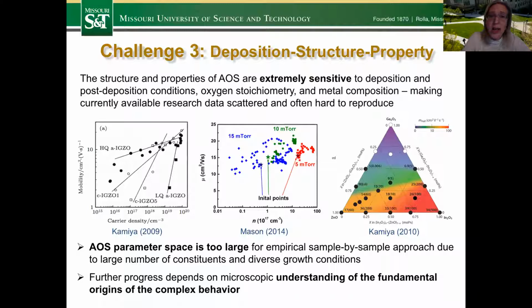Finally, challenge number 3. And these are complex deposition structure properties. So these materials have been studied for quite a while, and still there is a huge gap in understanding and predicting the properties. And we know both from experiment and theory that the structure and properties of these materials are extremely sensitive to deposition conditions, pre and post during the deposition conditions, oxygen stoichiometry, metal composition. And that makes the available research data quite scattered and often hard to reproduce.